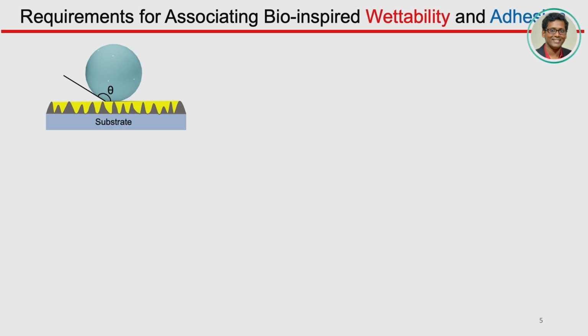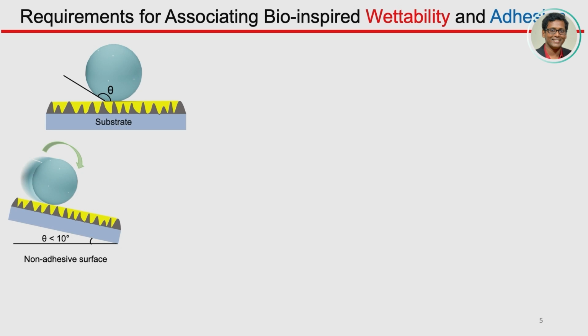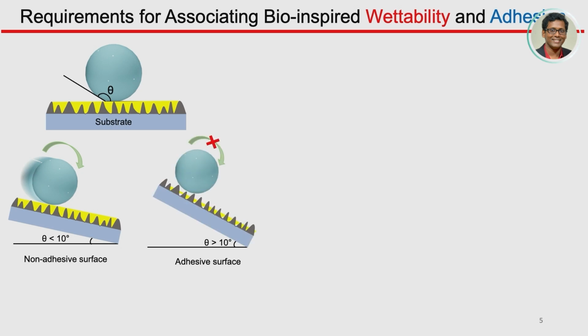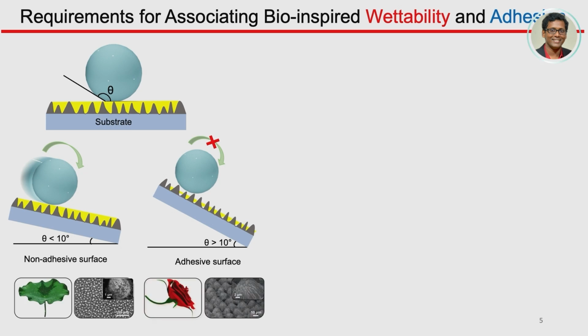Now, when we talk about extreme water repellency, often we forget about another interesting property, that is the adhesion of this liquid on the surface, and that has a lot to do. So this particular property can be further classified into two categories. One is non-adhesive superhydrophobicity, or extreme liquid repellence with the ability of flawless rolling at a very low tilting angle of the substrate, where the tilting angle will be less than 10 degrees, whereas in the other case the tilting angle will be way higher to roll this same beaded liquid droplet, whether it is water or oil, depending on what kind of interfaces you are dealing with. And if you see, nature has these kinds of examples. So the lotus leaf is an example of non-adhesive superhydrophobicity, and the rose petal is an example of adhesive superhydrophobicity.